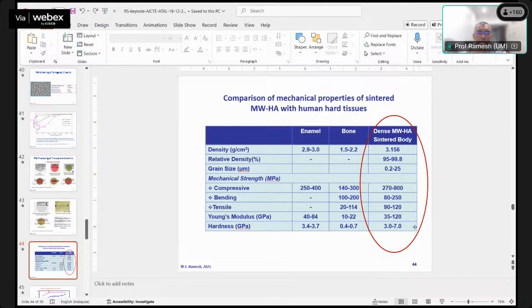These are some of the mechanical properties. So if you look, compressive strength can go up to about 900 megapascal, bending strength up to 250 megapascal, tensile up to 120. So hydroxyapatite is quite weak in tensile loading as compared to the bone. And Young's modulus is very, very high. And this is one area that we must take care of, because if we put an implant where the maximum load is undertaken by the implant material and not by the natural bone material,